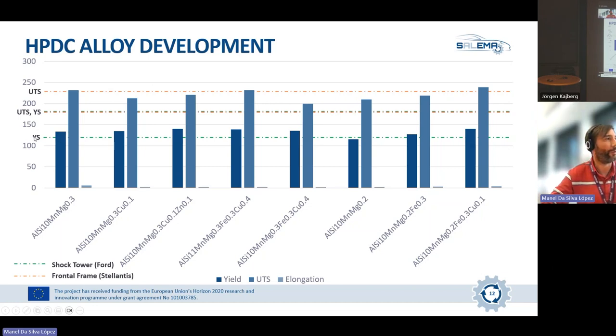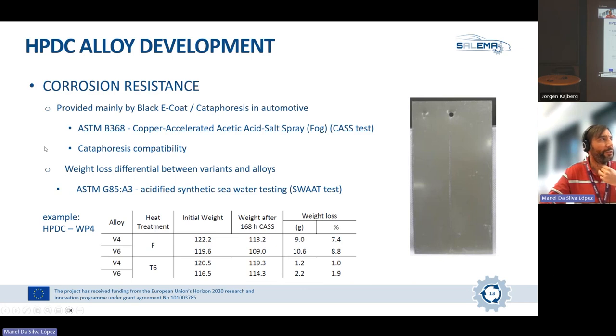Here you have the requirements of our demonstrators, the shock tower proposed by Ford and the frontal frame from Stellantis, from Fiat. We could meet the requirements from the shock tower in terms of yield strength and ultimate tensile strength, even without heat treatment for most of the alloy variants. We had bigger problems with the requirements from the frontal frame, but with a heat treatment we should be able to meet them. And actually, we were able to meet these requirements. The main issue was related with elongation, but we are going to deal with that later on.